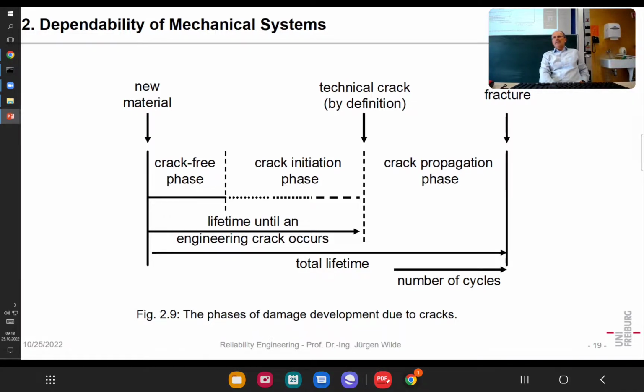And in that way, when the crack has been formed, the crack will grow. And you could say, depending on the stress level, it will grow between a nanometer per cycle and a micrometer per cycle. It just becomes longer. And then when it is long enough and the part is weak enough, it will fail